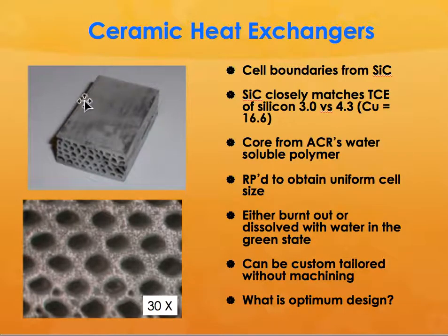So here is a solid piece. The advantage is that this ceramic material closely matches the coefficient of thermal expansion of silicon, versus some of the newer materials like gallium nitride or aluminum nitride and things like that. By using some kind of liquid coolant in that, you can remove up to 500 to 1000 watts per centimeter squared. So you remove that much heat.